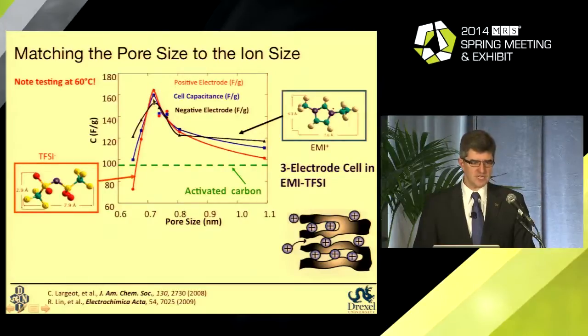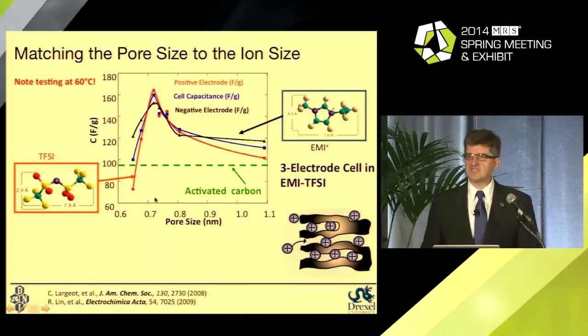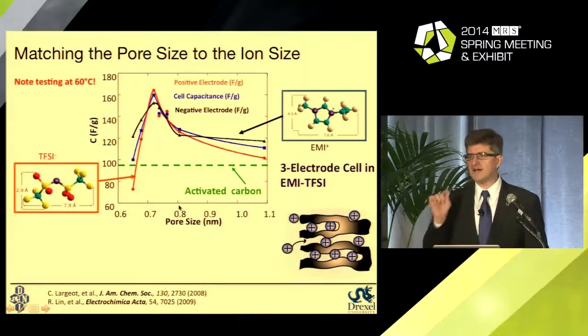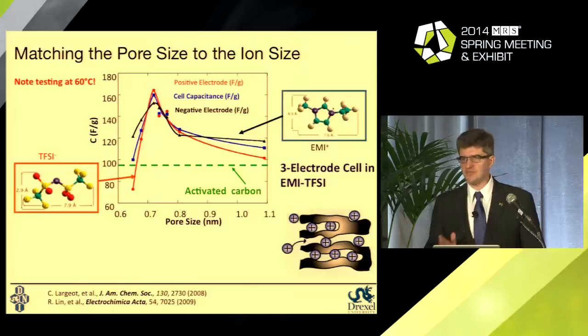We found that again, the maximum in capacitance is observed at the pore size virtually perfectly matching the ion size. However, I wanted to attract your attention to this scale. You see, a change of the pore size by 1 angstrom leads to about 50% change in capacitance. When pores are too small, ions just simply cannot go into pores. When pores are too large, you still cannot fit more than 1 ion in, say, a 1 nanometer pore if the ion size is 7 angstroms here.